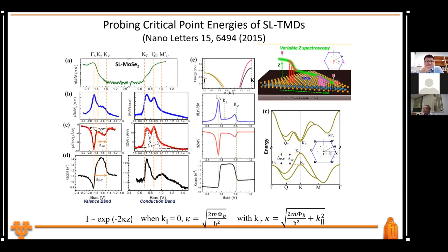So if you do that, then you can use the lock-in amplifier to look at the dI/dV, and that gives you roughly the density of states. It looks like this. Then you will see this kind of step. If you plot it as dZ/dV, then you will see this sharp dip. That's when you pass through the gamma point, then go back up here, then have another threshold here, which is the K point.